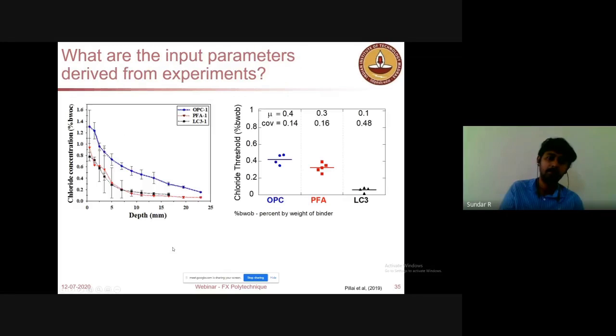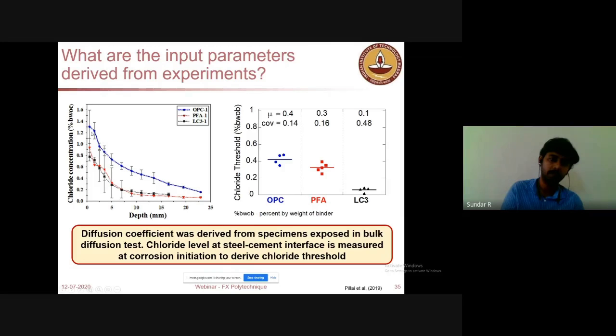And this is how we calculate the diffusion coefficient. We take powder from the concrete at the surface, and then measure the chloride levels up to the steel interface. If you have a cover depth of 25, you take chloride measurements at every interval, and then calculate the diffusion coefficient. Similarly, this is the chloride threshold, the amount of chloride required to initiate corrosion, which has also been calculated based on the corrosion test. These 2 are the more critical parameters governing chloride-induced corrosion.